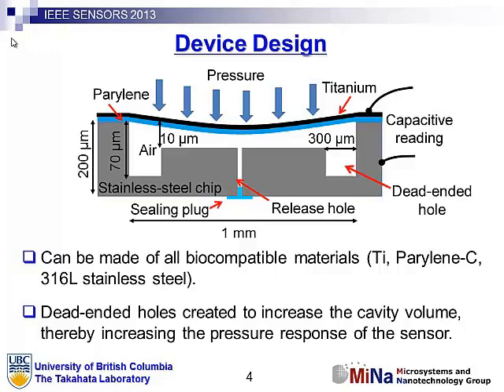It says 316 here, but actually for the devices shown in this, it's 304. And then there is a Parylene layer in blue, which forms the dielectric of the capacitor. And then the top electrode is titanium that was e-beam deposited.